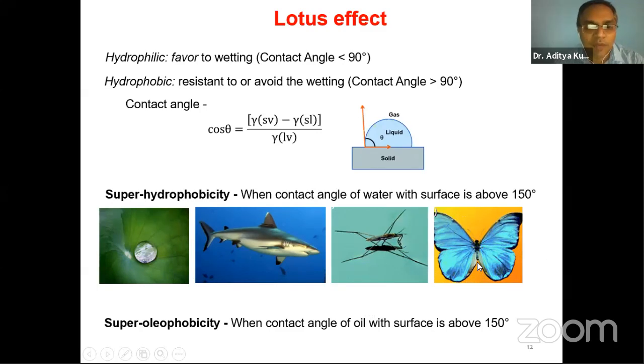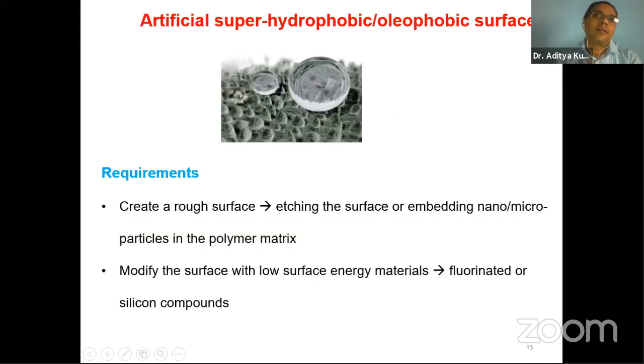Right. In nature, we have lots of examples: the legs of mosquitoes, shark skin, butterfly wings, and lotus leaves. Now, how do we create these super hydrophobic surfaces or super oleophobic surfaces in practical applications? With careful observation, scientists have seen that this surface has beautiful nanostructures. So if you create this nanostructure, and of course you have to have some low surface energy material, because of this low surface energy material combined with roughness, the water goes upward. So how do you create it artificially? You need a rough surface, and a low surface energy material on the surface.